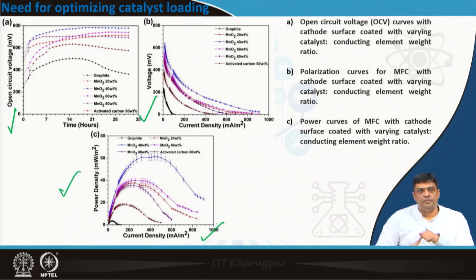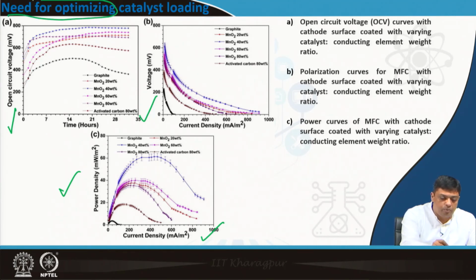We have been continuously saying that use catalyst, but that does not mean that you can use any amount of catalyst. The loading of the catalyst on the electrode is also critical, and the loading fraction becomes even more critical, because please remember, catalysts do not initiate the reaction, they just increase the reaction rate. The initiation of the reaction is actually occurring at the electrode surface. So, if you coat the whole surface with the catalyst, then the reaction will not get initiated. So, it is also important to optimize the catalyst loading.